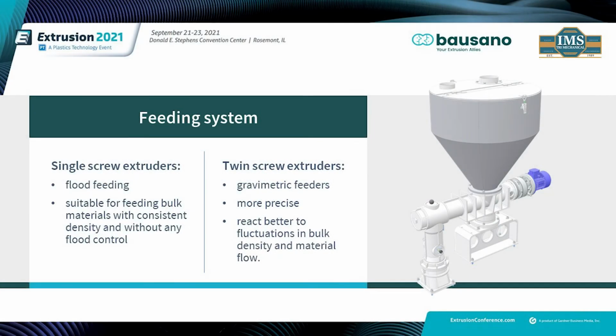A typical twin screw extruder configuration for the plastic includes the material feeding system, the melting, and the mixing sections. Before recycled materials can be processed, the waste plastic must be gathered, cleaned, and then separated according to type. From this, waste is ground up and then can be delivered via conveying lines and feeders to the compounding process. In any recycling process, the material and waste plastics can be heterogeneous in size, in form, and in bulk density. Therefore, the correct choice of feeding technology is very important for ensuring the best results.